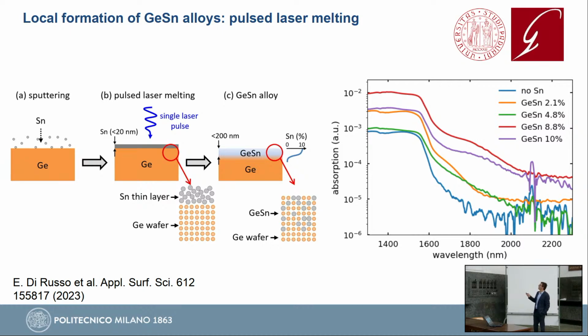And so these are preliminary absorption spectra of layers with germanium tin of different content, and we see that actually the absorption at longer wavelength is increasing. So we are able to see the first step of absorption at longer wavelengths. So we are continuing this work, trying to have a thicker germanium tin layer.